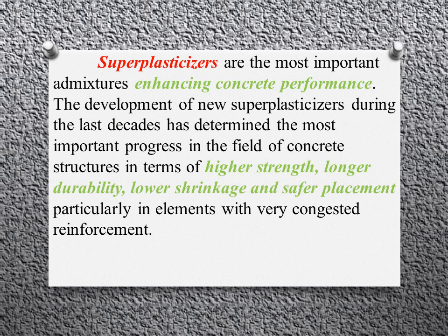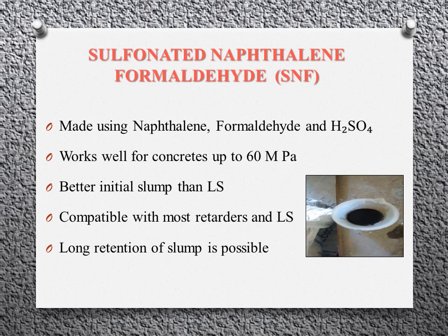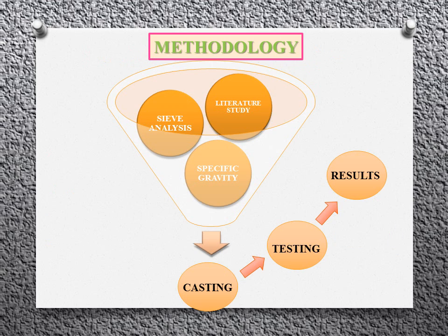Superplasticizers can greatly enhance concrete performance. They can give high strength, durability, low shrinkage and safer placement. The properties and nature of SNF are as shown. It's made using naphthalene, formaldehyde and sulfuric acid. It works well for concretes up to 60 megapascal. It has better initial slump than lignosulfonates. Long retention of slump is possible.